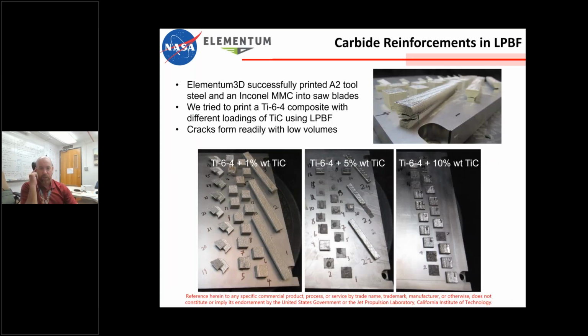We wanted to make this cutting tool out of a titanium carbide metal matrix composite in Ti-6-4. So, part of doing alloy development is trying to learn parameters. So we worked with Elementum to try to develop Ti-carbide loaded Ti-6-4, and it didn't work very well in powder bed fusion with high loadings of titanium carbide, which we were hoping to get, 40, 50% loadings.